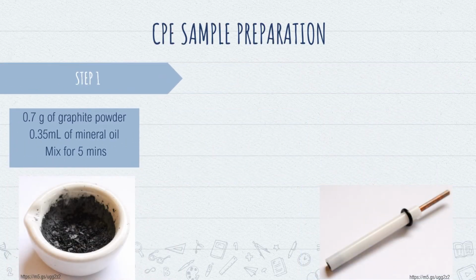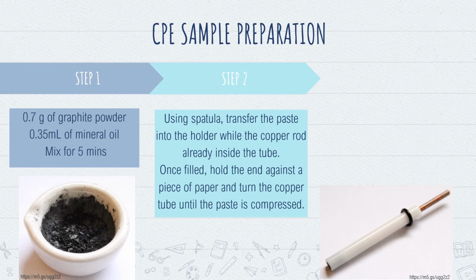Once the holder is ready, the carbon paste electrode can be prepared by mixing the graphite powder and mineral oil at a ratio of 70-30. The first step in this process is to weigh out 0.7 grams of graphite powder and place it in the mortar. 0.3 grams of mineral oil, or approximately 0.35 milliliters, was added and mixed for at least 5 minutes to make the paste. Next, using a small plastic spatula, the paste is transferred to the holder.